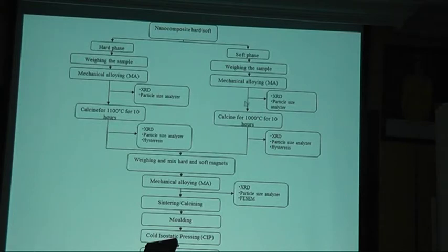The method is similar to what all of you do. We just have to be concerned about the temperature of sintering. I put it as calcine because we do heat treatment in powder. We cannot do it in pellet because after that we have to crush, because we have to mix. So better we sinter in powder. We mix soft and hard after we separately make the hard phase and soft phase. I think it will be very tiring work, because we have to do almost double work, for the soft phase and for the hard, and then combine. Then mechanical alloying, sintering or calcining, in powder or in pellet, molding and characterize.